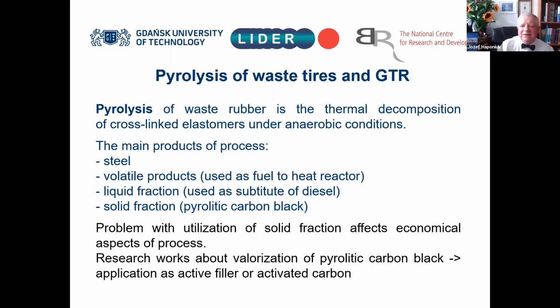Pyrolysis of waste tires and GTR is a rather positive way of utilization of waste rubber because of high energy content of waste rubber, and we obtain energy, still some volatile products which are used as fuel, liquid fraction used as substitute of diesel oil, and solid fraction pyrolytic carbon black. And this method is economical after maybe 3 to 5 years of using the installation.